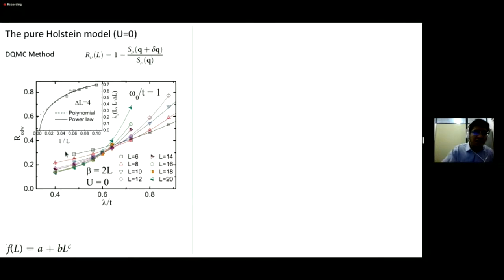So we did this analysis for many different lattice sizes, and what we saw was basically that the extrapolation, or in other words, the finite size scaling analysis of these crossing points, leads to a zero or almost zero critical electron-phonon coupling. So the point is not this 0.6, it is right here. So 0.1 or even zero here, depending on the way that you do your extrapolation.